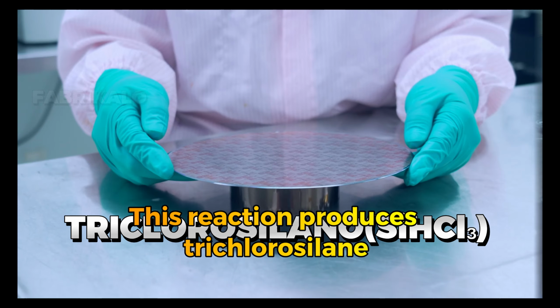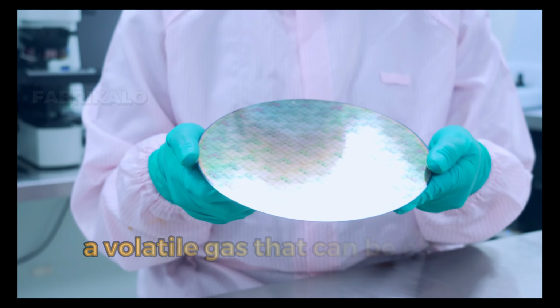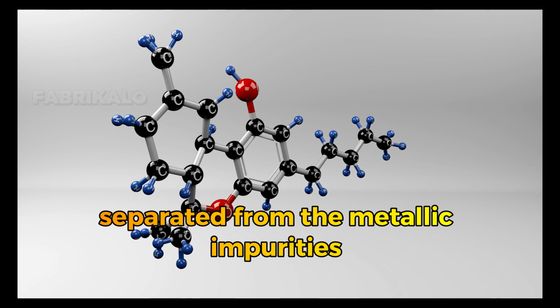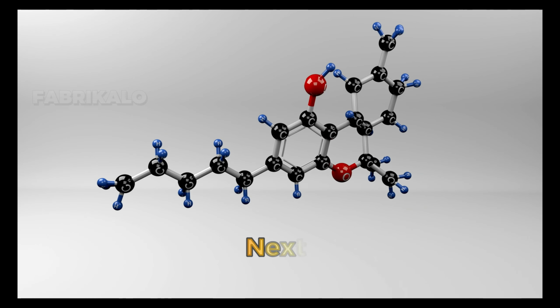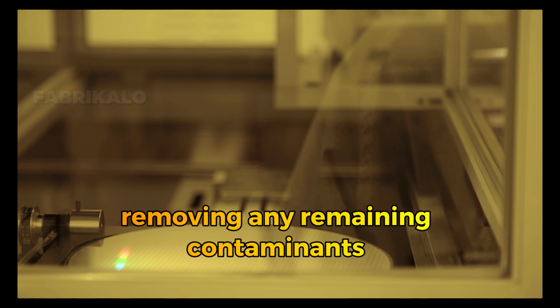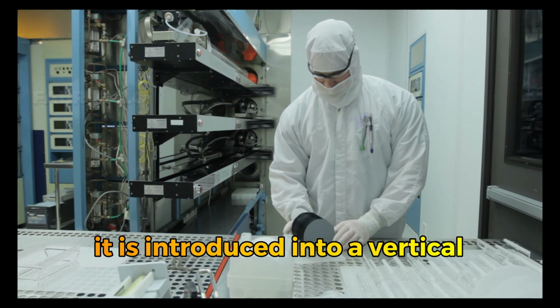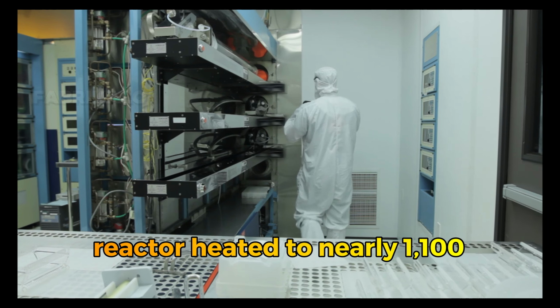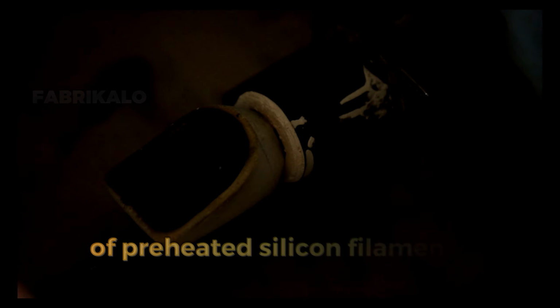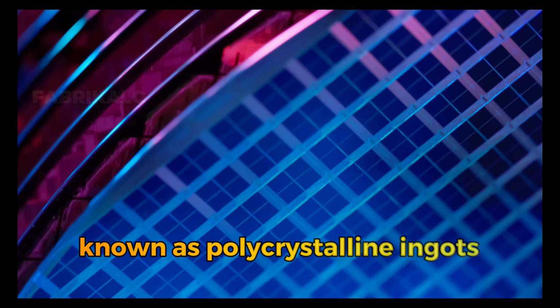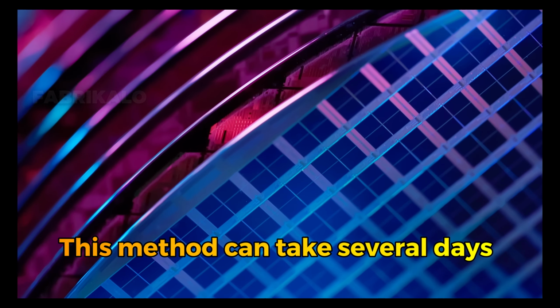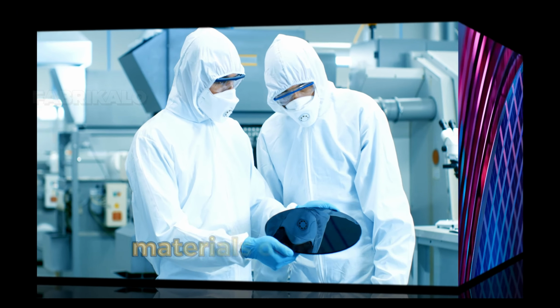This reaction produces trichlorosilane, SiHCl3, a volatile gas that can be easily separated from the metallic impurities present in the original silicon. Next, the trichlorosilane is purified through fractional distillation, removing any remaining contaminants. Once purified, it is introduced into a vertical reactor heated to nearly 1,100 degrees Celsius (2012 degrees Fahrenheit), where it decomposes in the presence of preheated silicon filaments. The result: silicon deposits layer by layer onto these filaments, forming ultrapure silicon bars, known as polycrystalline ingots. This method can take several days but produces one of the purest materials on the planet.